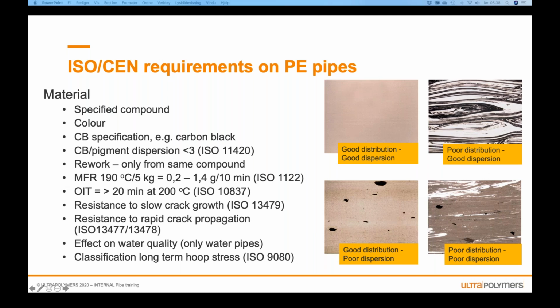And here are some different types of materials, which I often show. I will show it later also in this presentation, but it gives a good example that buying a black material, when you process it, you get a black pipe or a black rotomoulded product, but it's not necessarily good. What you want when you look at it in a microscope, you want to have an even distribution of the carbon black. And there are two ways that the carbon black or the carbon black master batch can ruin the material. So if you look at this picture at the upper right, the master batch and the carbon black is actually very good, but the extruder they are extruding it on is poor.